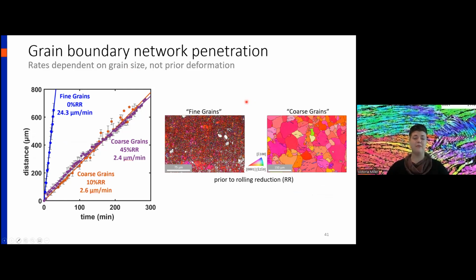So the rate of grain boundary penetration depends on grain size, but not so much on prior deformation. We looked at a few different microstructures: a fine-grained microstructure and a coarse-grained microstructure. And we considered 0% rolling reduction, 10% rolling reduction, and 45% rolling reduction. The coarse grains all followed one curve, regardless of rolling reduction, and your fine grains all followed a different curve, regardless of rolling reduction. And note, you get a linear grain boundary penetration distance with time.